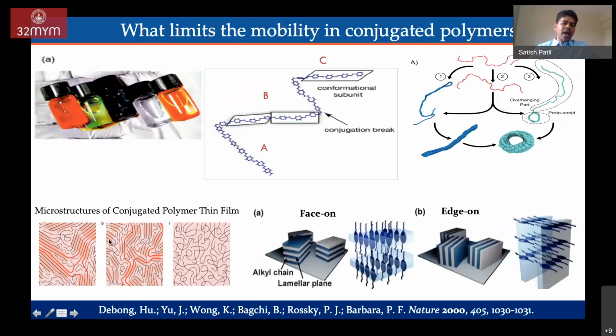And it has mixed domains. You have crystalline domains as well as amorphous domains. Mixed domains make it very difficult to address the questions in this kind of complex system. When you measure the electrical properties of a thin film of such a conjugated polymer, it is always challenging to correlate the electrical properties with the structural properties. As a result, these materials suffer from a very low charge carrier mobility.